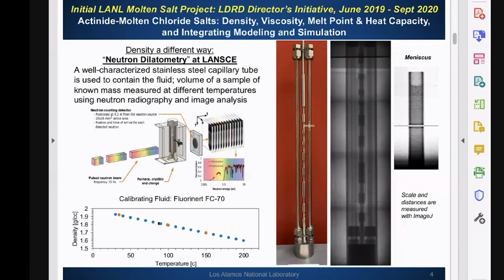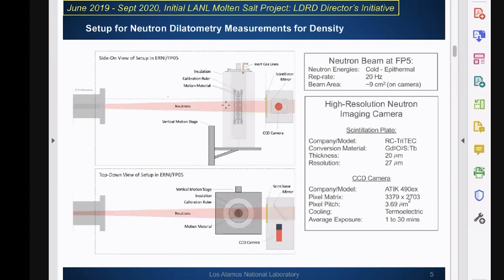So let's see. I also wanted to point out this interesting looking shaped machined piece in the center here. This is what we're calling our neutron ruler. It's basically machined with precise dimensions, and that helps orient us and provides a reference point at any position along the length. And so what you're looking at here is a series of images stitched together. So you can see the ruler in the center and the capillaries on either side. And then here you can see a zoom in of what the meniscus looks like at molten temperature. Our setup was calibrated with Fluorinert. It's a material that we use as a calibrating liquid at a relatively low temperature, but across a range of temperatures. And we found that we could match with only a difference of about 0.05%. So we proceeded on to our molten salt samples. Here's just a quick picture of the schematic of that setup that I just showed you.